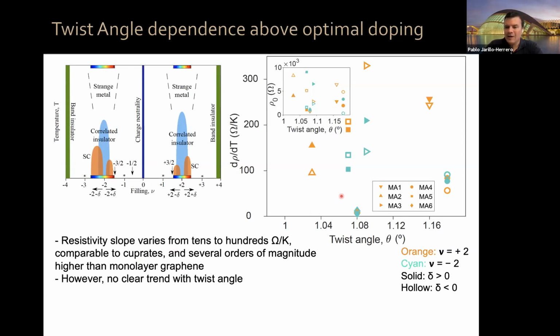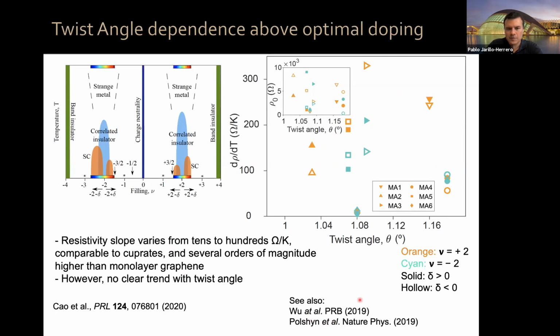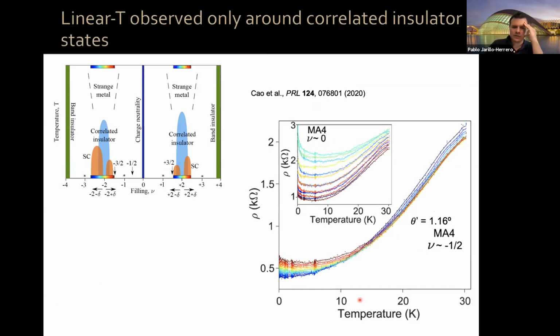Within this magic angle range, we didn't observe a clear trend with twist angle. But we explored only devices which were within the magic angle range, devices that exhibited superconductivity, etc. Now, you can also see other data by the group of Andrea Young and some early theoretical predictions. That linear behavior was seen within this density range.